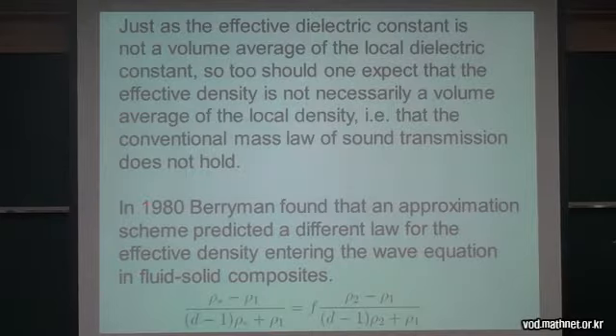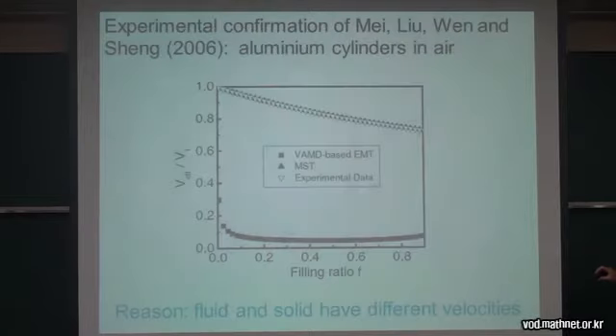And actually back in 1980, Berryman found an approximation scheme that predicted a different law for the effective densities. So that the effective density is not just a volume average of the two densities, but is given by this complicated formula here. And actually in 2006, Mei, Liu, Wen, and Sheng provided experimental demonstration for aluminium cylinders in air. So this was the wave velocity, and this was the experimental result up here, and these are the results if you assume that the density was just a volume average density. And so there's a big difference actually.